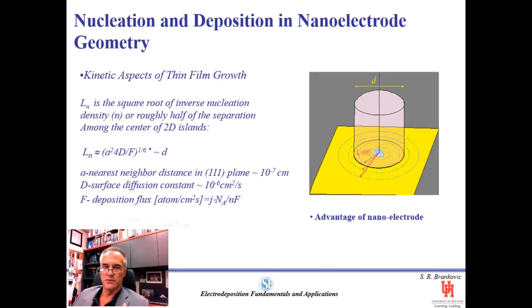It's also important to appreciate one thing: based on this relation I just described, when we have electrode geometry which is really small, where the dimensions of the electrode scale with the average distance between nuclei, or L sub n, then we can have peculiar conditions where, depending on our flux of the deposition current density, we can nucleate one or many nuclei within the boundaries of the nano-confinement of our electrode.